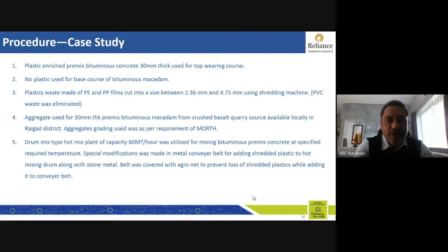The plastic enriched bituminous concrete, 30 millimeter thick, used for the top wearing course alone. We do not advocate that waste plastic should be used in all the layers of road construction. We are using it only for the layer which is susceptible to the environment and to the traffic conditions. So we made these waste plastics in different material. We classified polyethylene and polypropylene material from the multi-layered plastic.